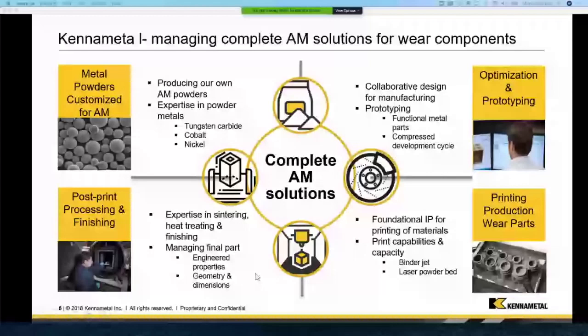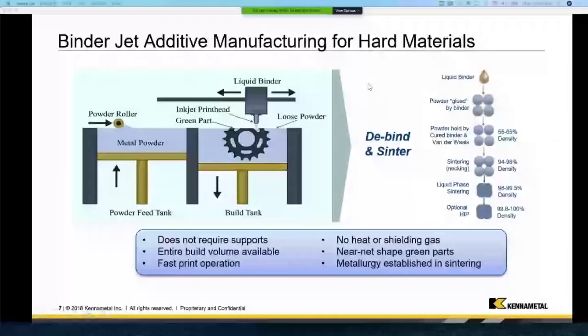So for our hard materials, as well as some of the stellites that we're currently printing, we are primarily focusing on binder jet technology. As a brief description, you have your powder reservoir or tank distributing that material into your build tank or build box. In your build box, layer by layer, you're putting down a very thin layer of liquid binder on the powder to create your bound layer, where the binder is gluing that powder together layer by layer. What you end up with is a green part that then has to go through debinding, burning off that binder, and sintering to your final metallurgical properties.